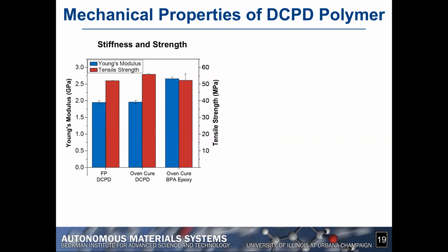So how good is the material that we make using this technique? Well, first we looked at the mechanical properties of just the polymer itself, the DCPD polymer. On this graph here, you have 3 different types of situation. On the left side, we look at the properties of frontal polymerized DCPD. The 2 middle bars correspond to the oven cured DCPD, and on the right side, you have the properties of epoxy, done using a conventional approach. The blue bars correspond to the Young's modulus, and the red ones correspond to the tensile strength.